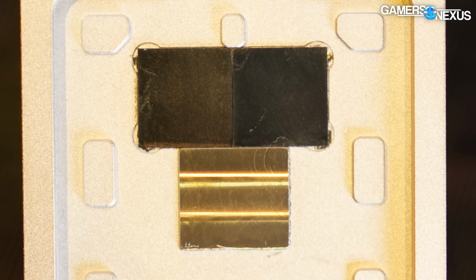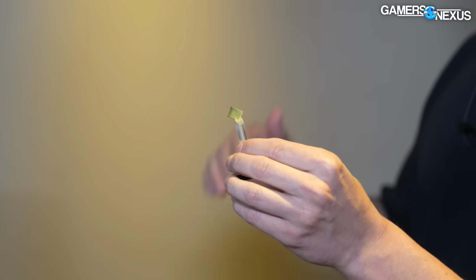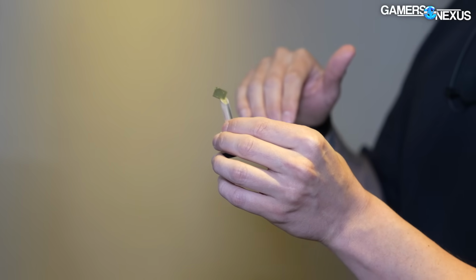You can see it's translucent, but because it's pure carbon, liquid metal does not stick to the surface. That was one of the biggest challenges. So we had to find a way to metal coat the diamond. So this is a metal coated diamond to be able to have the liquid metal stick to the surface. What is it that dictates whether it can stick or not? In German, if I would translate it, it's like the activeness of the surface, like how chemically active the surface is. What's the German word? Oberflächenaktivität.